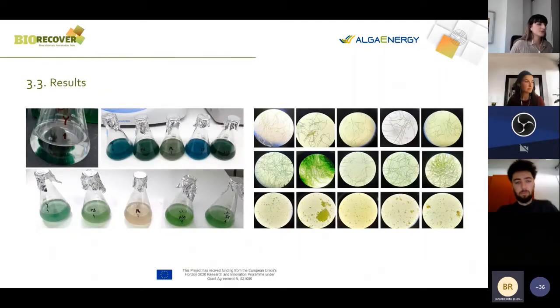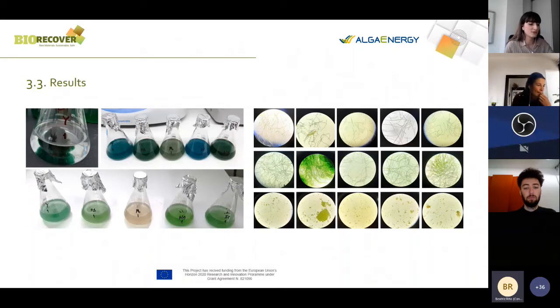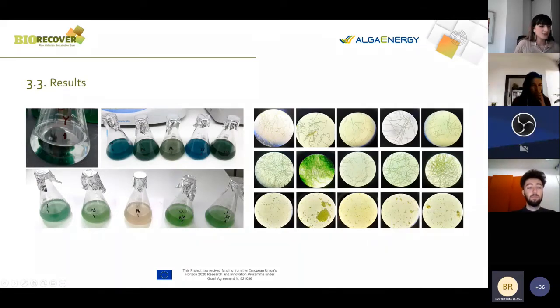The qualitative results of these experiments can be seen in these images. Significant color changes were observed in the different microalgae after incubation with the leachate. In some cases, these color changes are due to the production of pigments typical of certain microalgae, whose cellular structure is altered after contact with metals. If observed under a microscope, certain aggregations can be distinguished, especially in the case of contact with yttrium. Next slide, please.